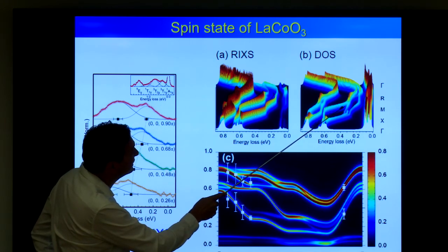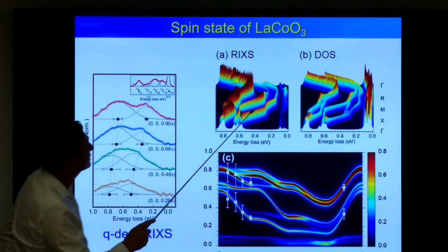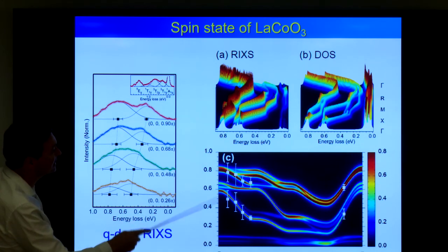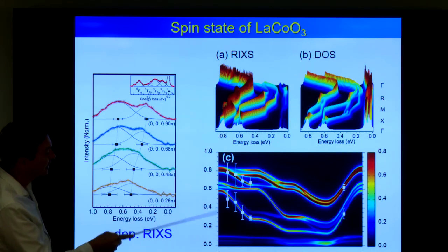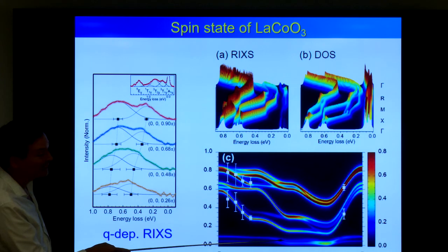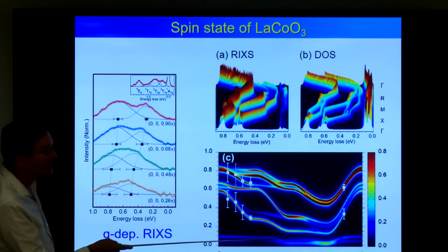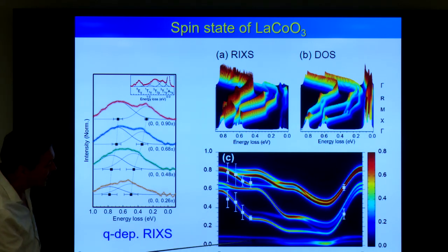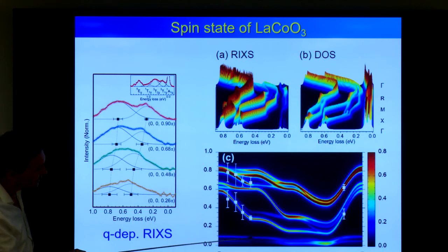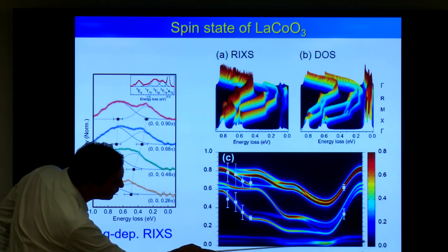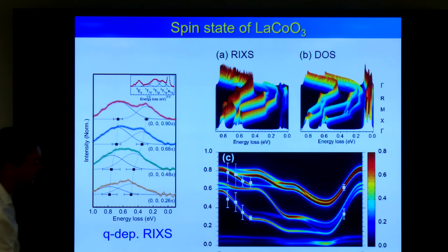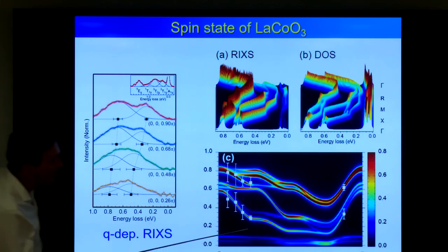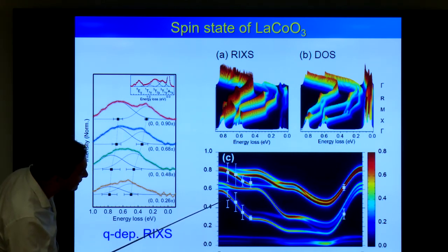This is the density of states. This is multiplied by matrix elements, so that's the RIXS, so that's what we expect. And then this is folded out, so you can think of it as a band structure, but this is again not a real band structure, it's the electron-hole excitations. And now you see here between 0 and 0.1, that's the low spin and the high spin state. So they are essentially horizontal because they do not couple, they are essentially atomic states. But this is the intermediate spin state. So this has a very large dispersion.